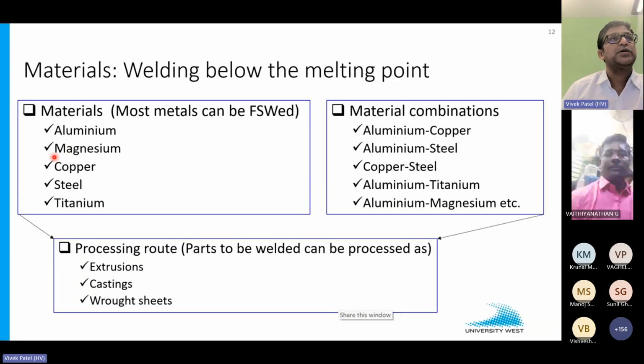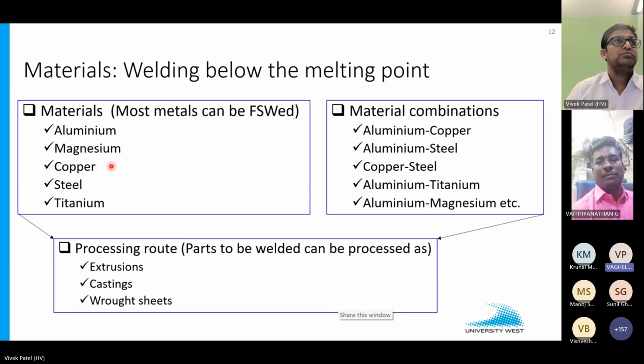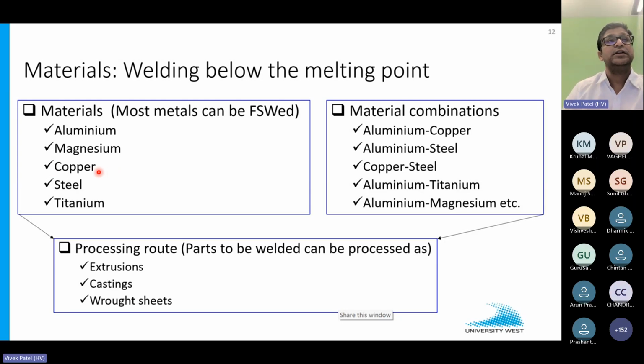Magnesium also, it's quite evident. We find a lot of research articles and a lot of space applications now where magnesium alloys are welded by friction stir. Copper, of course, it is mature for copper also. But for welding of copper, the tool material plays a significant role. So you should have a different tool material when you are welding aluminum and copper.